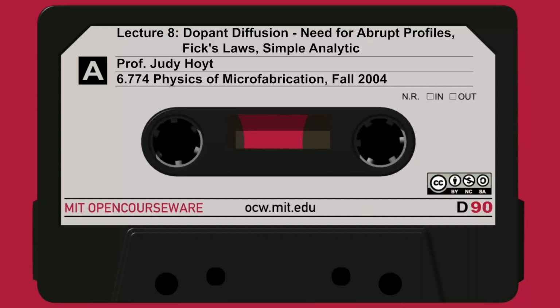So if we have a situation where we have a constant surface concentration, then the solution to the diffusion equation is just the right-hand side of the above figure. An example of this might be the case where we're doing diffusion from a gas ambient into the solid, with the gas concentration above the solubility of the dopant. Then in that case, at the surface of the silicon wafer, the concentration of the dopant is fixed at the solubility, so it's constant.